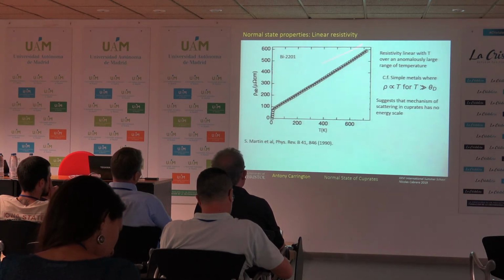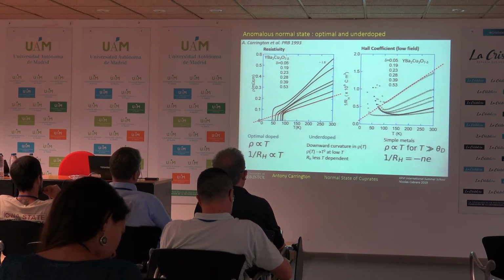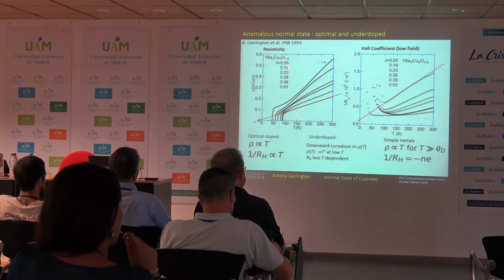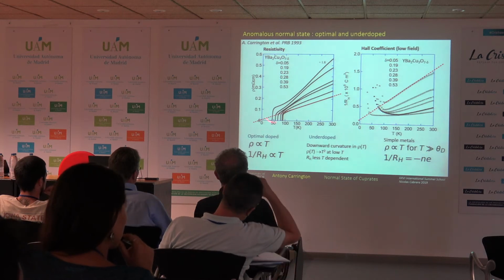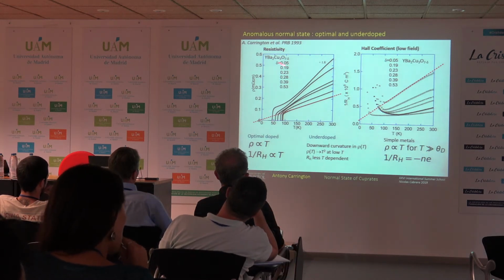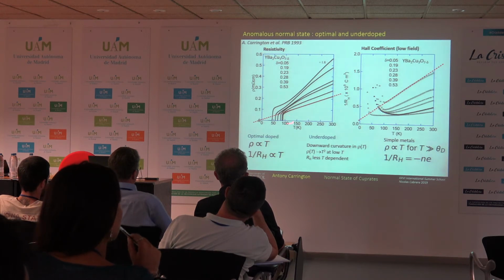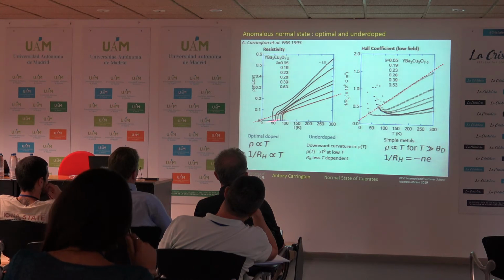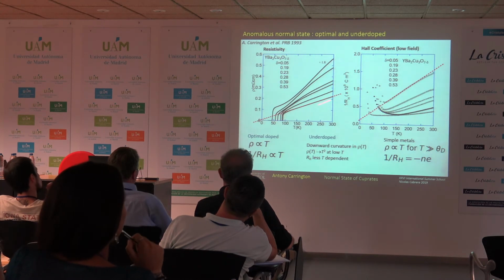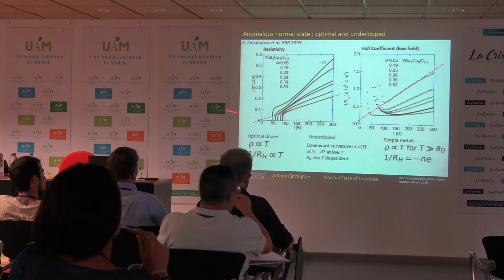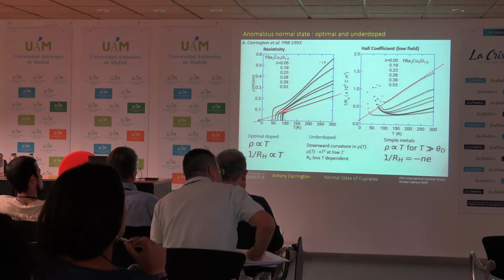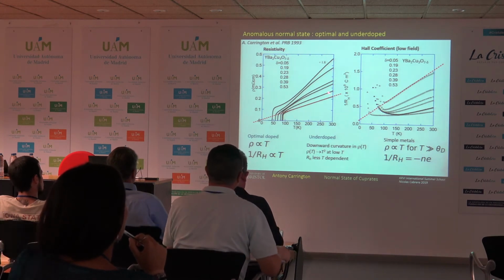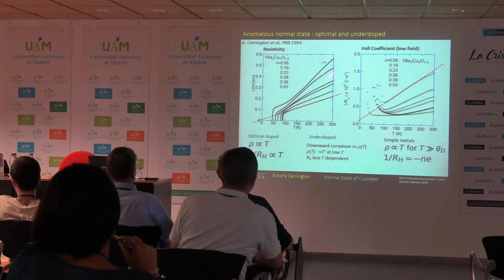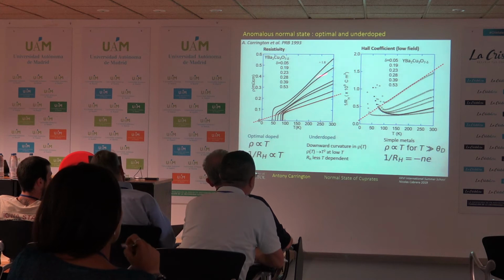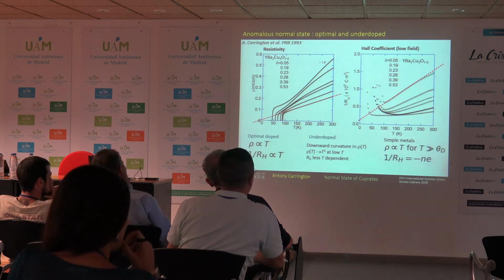What I just showed you is for one particular disordered cuprate; this is what happens more generally. This is some data here for YBCO as TC changes. So at optimal doping, with the oxygen deficiency essentially 0, again it seems to be linear. It's cut off by the fact that TC is 100 Kelvin, but it seems to be linear and goes through 0 essentially, indicating that it has a very low residual resistivity. But as you go away from optimal doping, the resistivity changes shape, and it adopts this kind of S shape. So we'll come back to that in a minute.